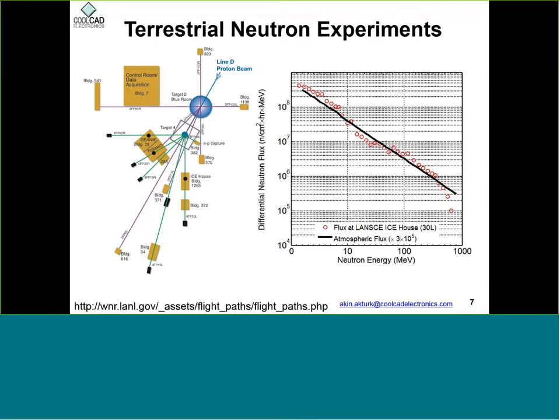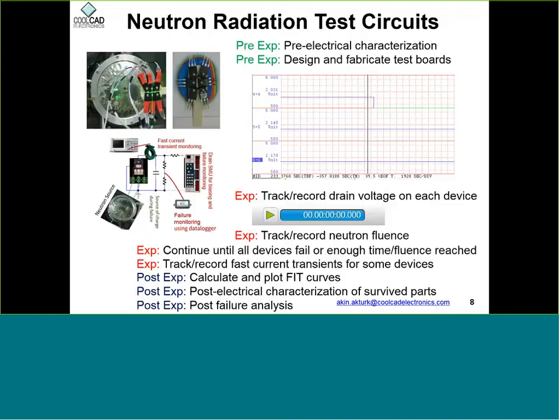This center has 2 beam outputs that simulate the terrestrial neutron background radiation. On the right, you can see how it matches with the atmospheric neutrons. At this place, you can have neutrons up to 600 MeV energy. Beyond that, there's a cutoff. And the LANSCE neutron source is the best in the world, and there aren't too many of these sources because it's really hard to simulate very high energy neutrons and also achieve a spectrum that's similar to the atmospheric neutron spectrum.